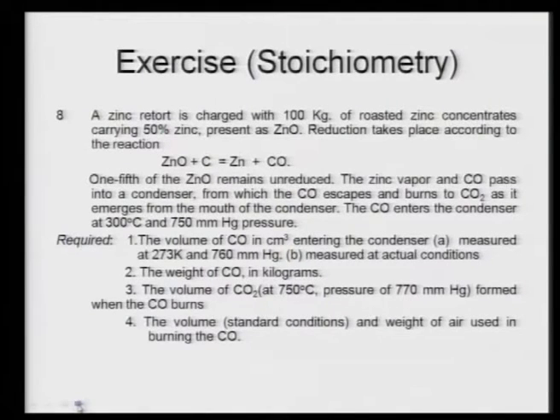A zinc retort is charged with 100 kg of roasted zinc concentrate carrying 50% zinc, present as ZnO. The reduction equation is given. Now, some of the problems: it says 1/5 of the ZnO remains unreduced. The zinc vapor and CO pass into a condenser from which the CO escapes and burns to CO2 as it emerges from the mouth of the condenser.